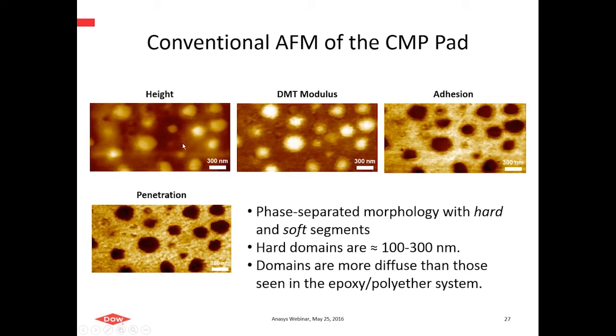We have a phase-separated morphology again, and in this case, the phase separation is a result of the two types of chemistries in this polyurethane. We have more rigid isocyanate chemistries that we think lead to the harder domainal material, and then we have softer components associated with polyols or polyethers, like we'd seen before in the previous example. These react to form urethane linkages, and we think that enrichment of that urethane chemistry is likely present in these phase-separated domains. It's a little different than the last system. You see now we have more diffuse boundaries in this case, and a much finer phase-separated size. We're only 100 to 300 nanometers.